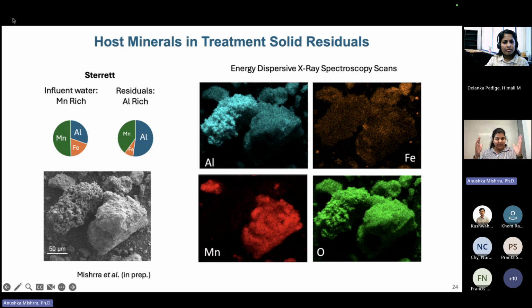So when we look under the microscope, SEM, and do energy dispersive X-ray spectroscopy scans, so EDS scans, which is basically creating elemental maps, we start seeing that aluminum and manganese are coexisting in these solids. There's possibility that manganese is covering aluminum solids. And we see also that iron is actually very low in concentration. So I've run these EDS scans on several solids that we have collected, and this is just one representative image that I'm showing over here.